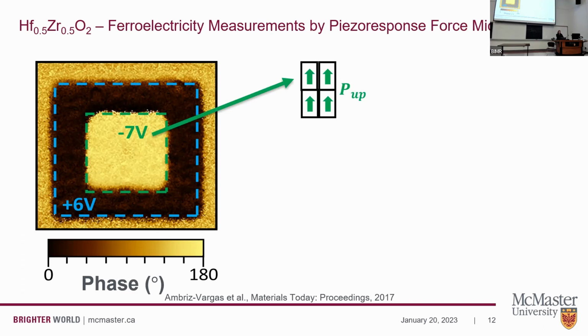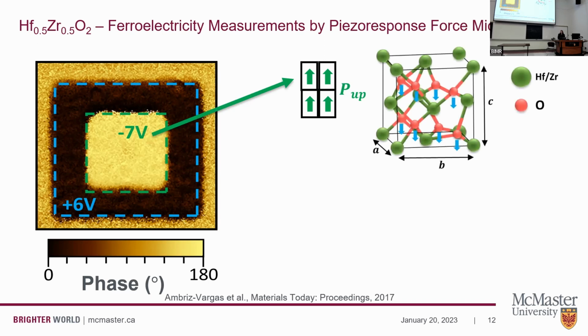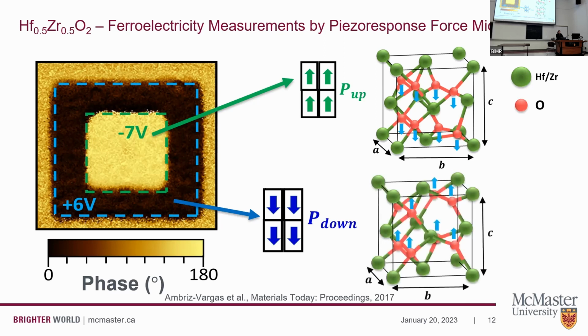Now, we have the polarization pointing up. This is due to a change and a shift in the atoms that form the crystal. Here we have the orthorhombic crystal structure of our hafnium zirconium oxide. The green atoms correspond to the hafnium and zirconium atoms, while the red ones correspond to the oxygen atoms. As we apply a voltage, we'll have a polarization that will point up. This is due to a displacement of the oxygen atoms towards the bottom, which in turn results in the polarization pointing the other way. If we apply this negative voltage, we have a shift of the oxygen atoms in red the other way, towards the top.